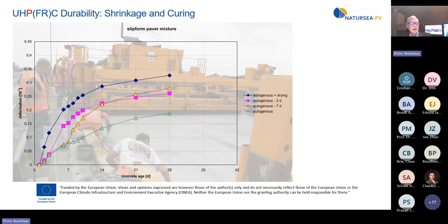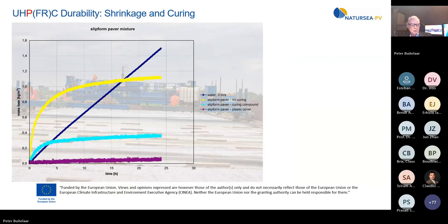Shrinkage and curing can significantly influence the durability of UHPC, especially when UHPC is used in an aggressive environment like offshore and on bridge decks. Evaporation of mixing water in UHPC with already a very low water binder ratio will result in unwanted shrinkage, cracks and delamination. The amount of evaporation of UHPC placed on large surfaces and the effect on the durability is often underestimated.